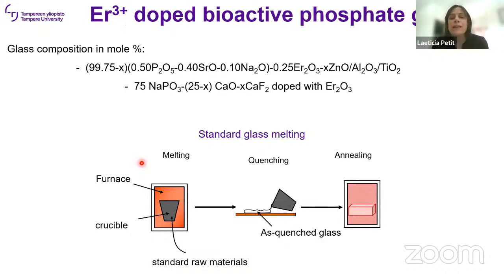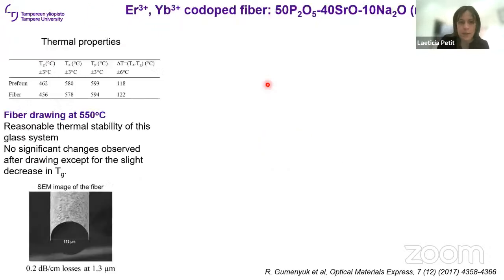So let me discuss what we did with these erbium doped phosphate glasses. These are the two glass systems that I decided to speak about today. The first one is a phosphate with sodium and strontium, and the other one is with calcium. The glasses that we make in my group use a standard melting process. We melt, quench, and anneal the glasses. So let's start first with this glass composition.